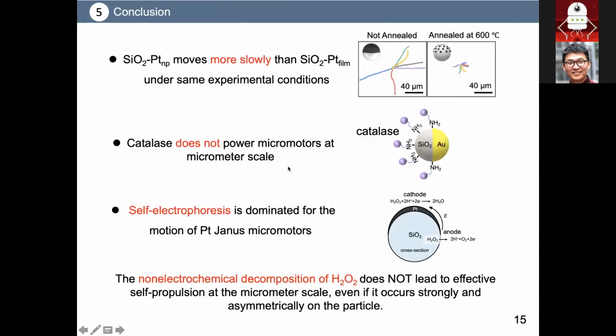To conclude, we propose that the non-electrochemical decomposition of hydrogen peroxide does not lead to effective self-propulsion at a micrometer scale, even if it occurs strongly and asymmetrically on the particle. This is supported by two evidences. First, silica-platinum nanoparticle moved more slowly than silica-platinum film in the same experiment under the same experimental conditions, and catalase does not power micromotors at a micrometer scale in the presence of hydrogen peroxide.